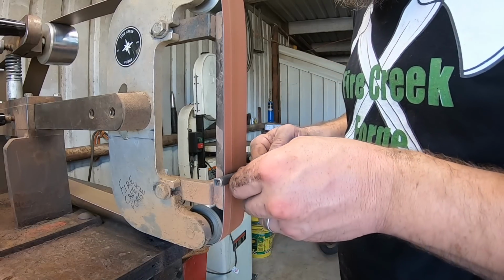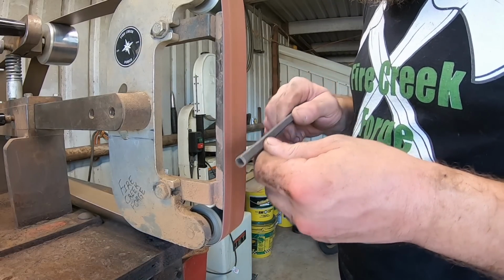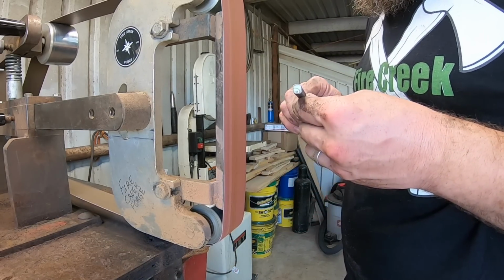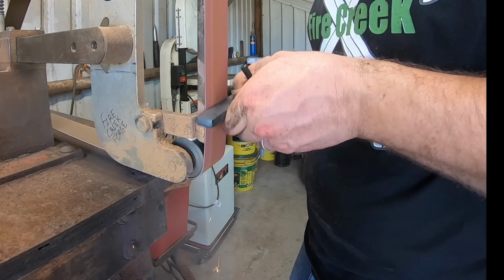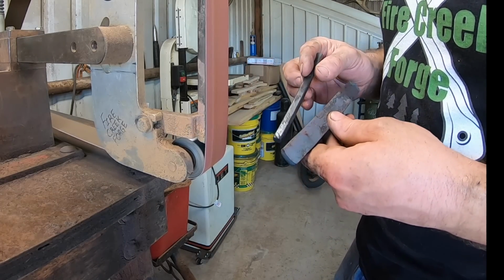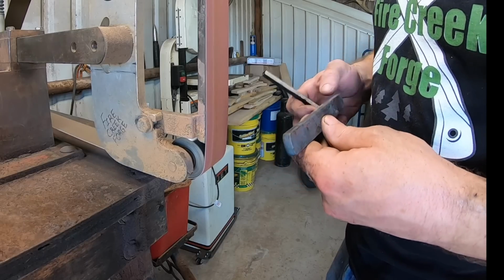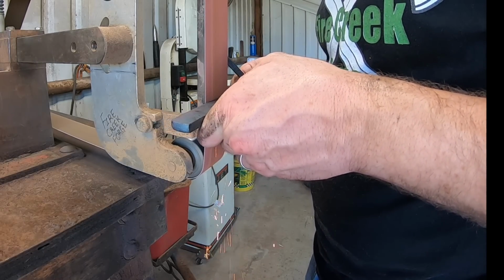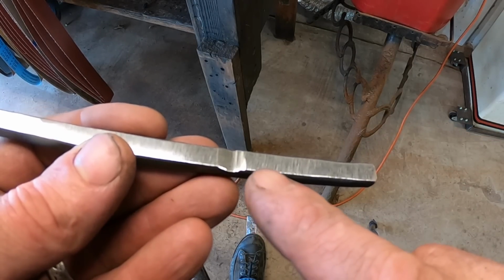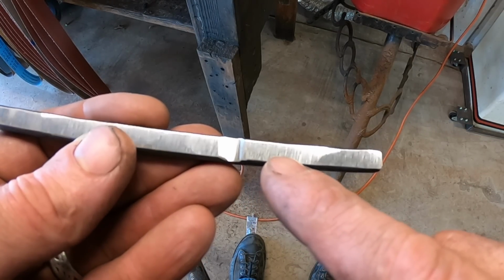So I let them cool down to a black heat, and then trying to hurry the process along a little bit, I dipped them in water, cooling down the rest of the way. That's totally fine for the high carbon steel billet there. But the tool steel did not handle it as well.